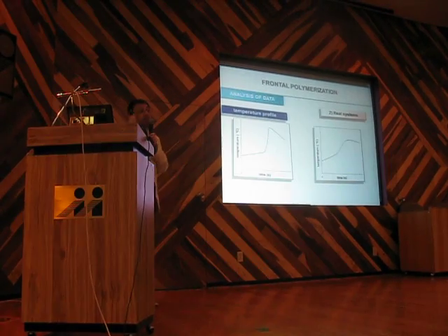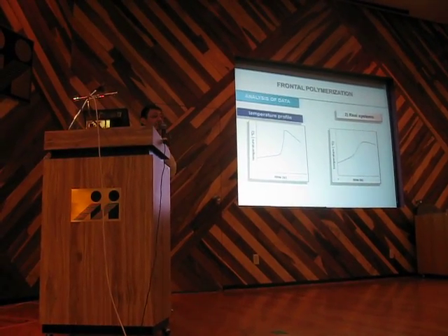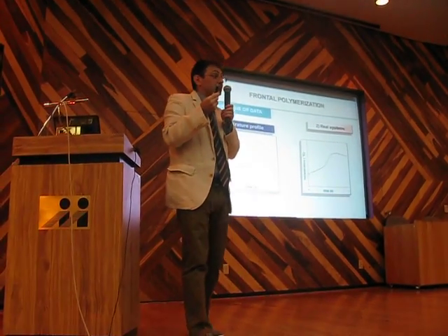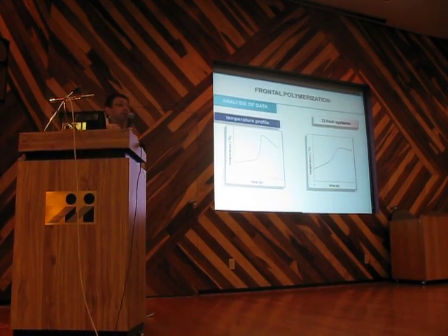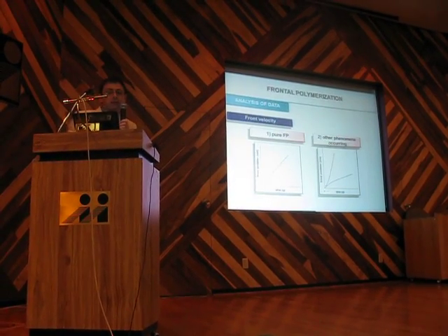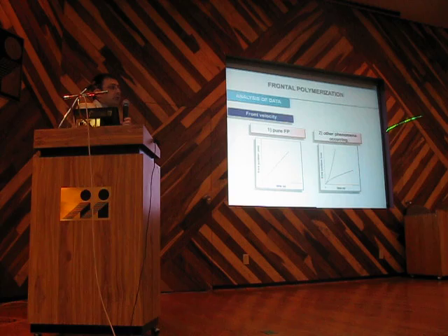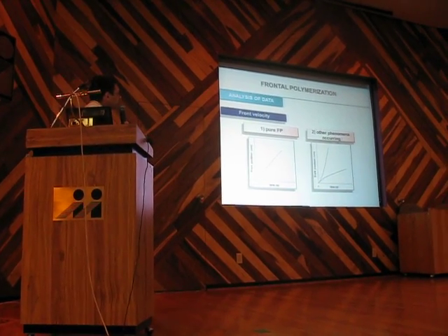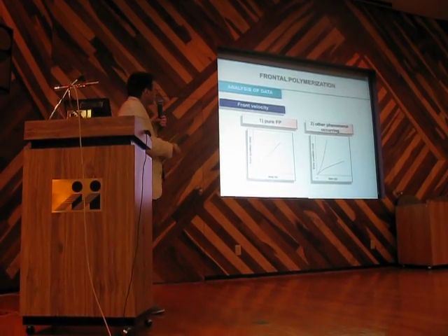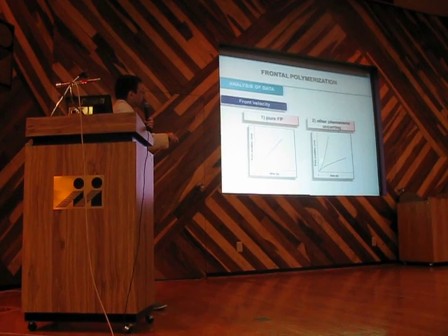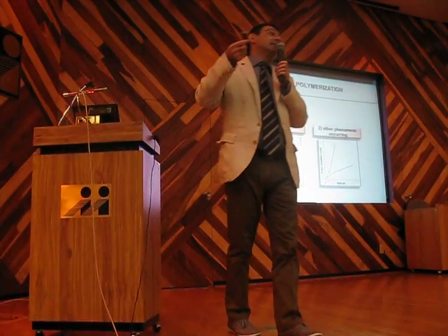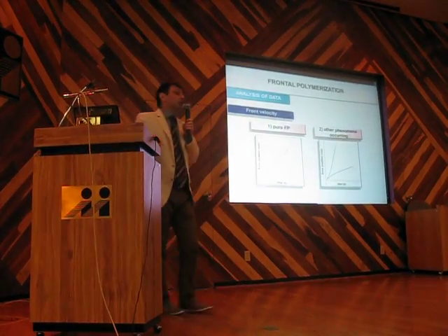Something else generally is polymerization which is occurring simultaneously. So we have two phenomena at the same time. And this is generally what we don't want. Analogous consideration can be done by considering the front position, because as I told you, a pure frontal polymerization is characterized by constant velocity, but sometimes we can observe that velocity is not constant. And again, it means that something else is occurring. So our frontal polymerization is not pure.